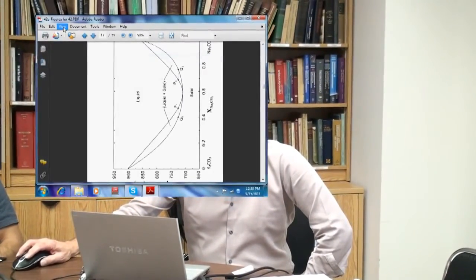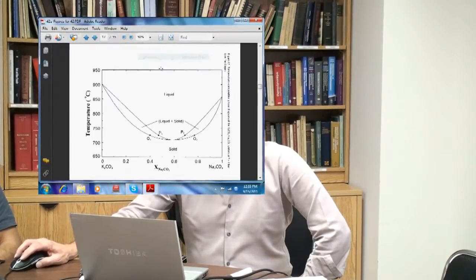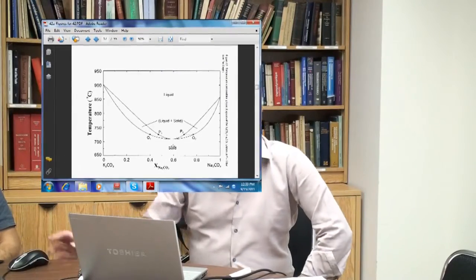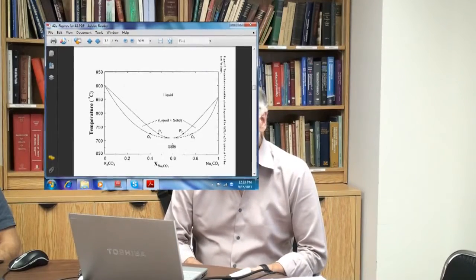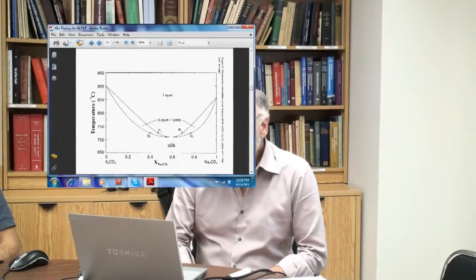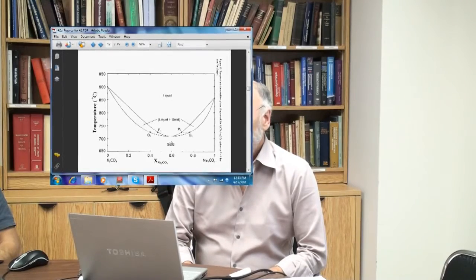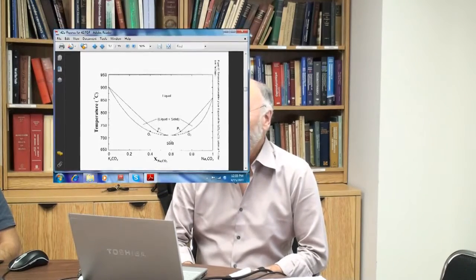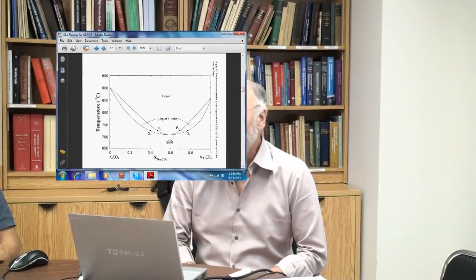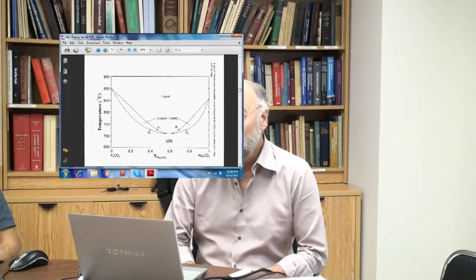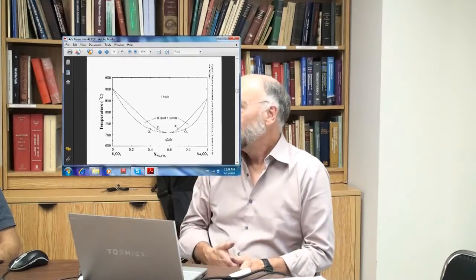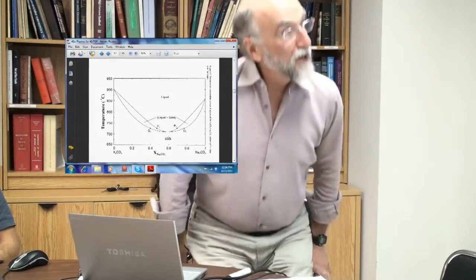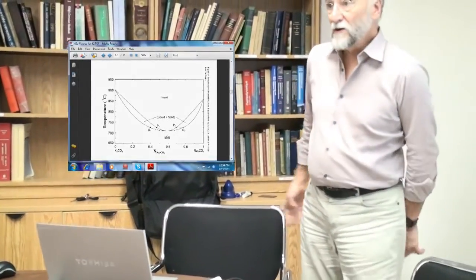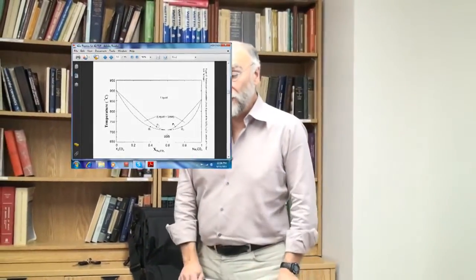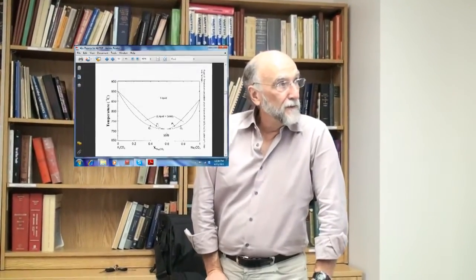Okay, that's the minimum temperature there. That is not a eutectic. If you cool the liquid down, it will freeze isothermally like a pure material. Okay, so it's a quasi one-component system, if you like, but it's not a eutectic. A eutectic is where liquid gives two solids. This liquid gives a solid at the same composition. It's just a point where things are right in balance. It's not a eutectic. It's not an invariant. It's a quasi one-component system, if you like. It's different from an invariant reaction in terms of the phase rule.